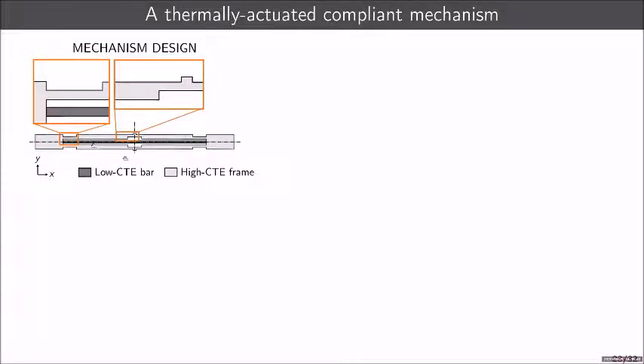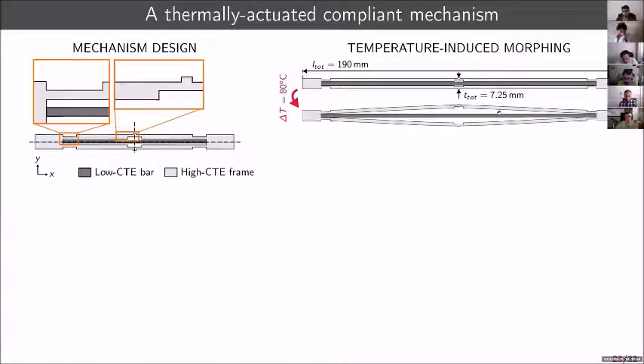The outer frame is made of aluminum and it's made of different parts. We have some bulky beams that are connected by flexible joints. What we have is that basically when temperature increases, the low CTE bar expands, and the two parts are jointed together. We assume that there is perfect bonding between aluminum and titanium. Once the titanium, the low CTE bar, expands, the high CTE part wants to expand even more, but it cannot expand in the lateral direction because it's constrained by the low CTE bar, and because of that, we have an out-of-plane deformation of the structure, as you can see over here. So we are able to increase the size of the structure in the vertical direction by a lot.